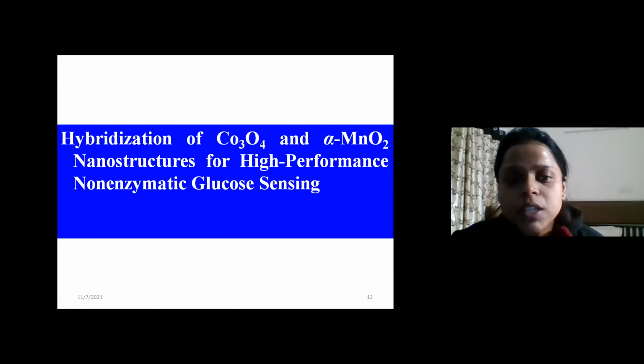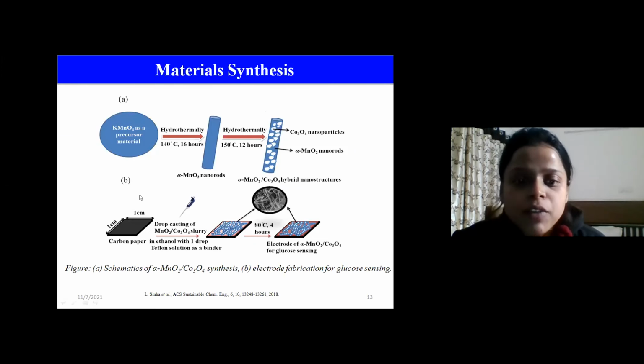So the first work is the hybridization of cobalt oxide and manganese oxide nanostructures for high performance glucose sensing. We have used a two-step hydrothermal method for the synthesis of alpha MnO2 nanorods, and again we have modified it by depositing Co3O4 nanoparticles over the alpha MnO2 nanorods. Now the electrode we have fabricated using a 1 × 1 centimeter carbon paper, and we have deposited MnO2 Co3O4 slurry over the electrode to investigate the electrochemical properties.